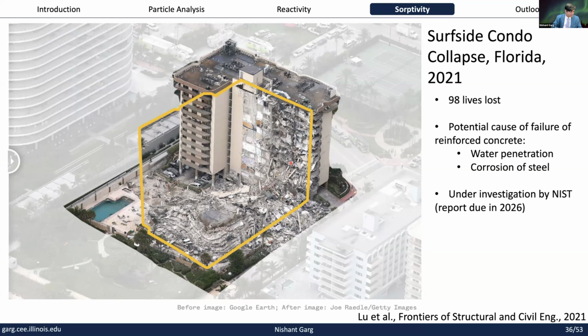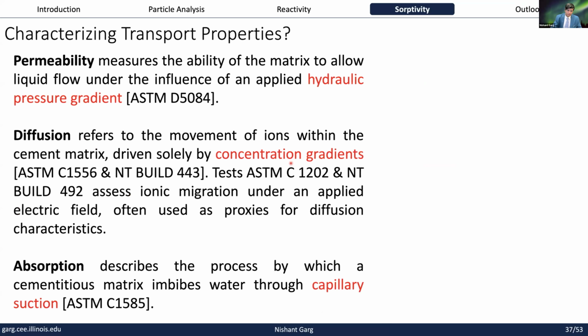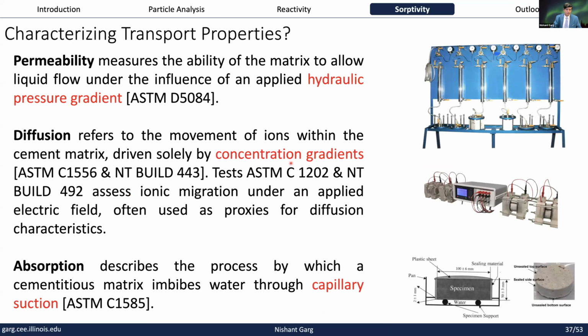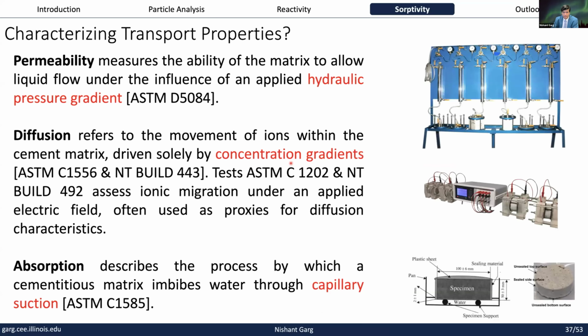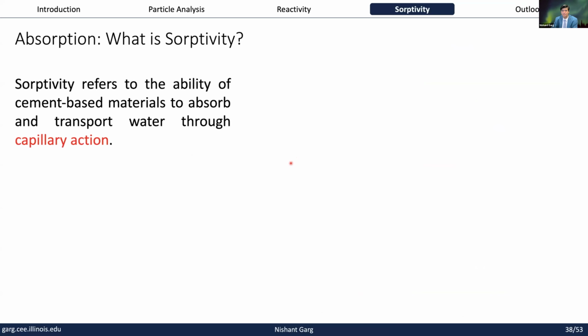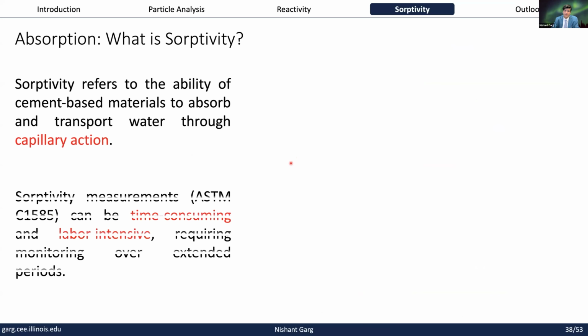Now, this is still actively under investigation by NIST, but if you go to their website and see what they're doing, one of the key tests they're doing is looking at the sorptivity of these systems, because ultimately how much water goes through concrete and reaches the rebar is a huge decider in how much corrosion will happen. So if you look at the transport properties, there are many different things of interest here, but what we care about is the absorption or the sorptivity, which we can define as follows: essentially the ability of these materials to absorb water and transport water through capillary action.